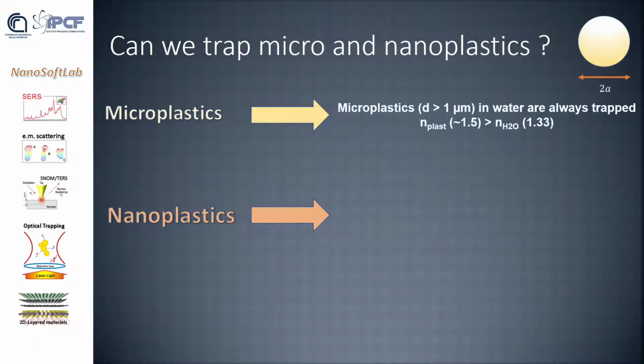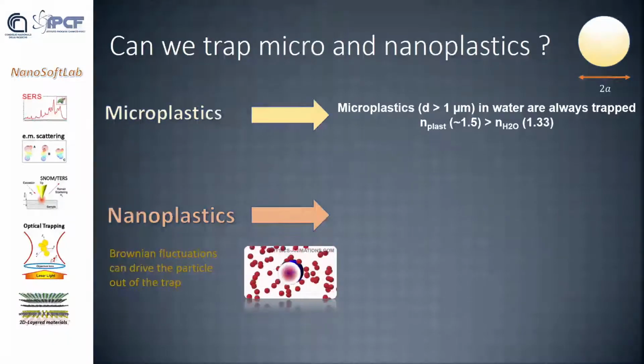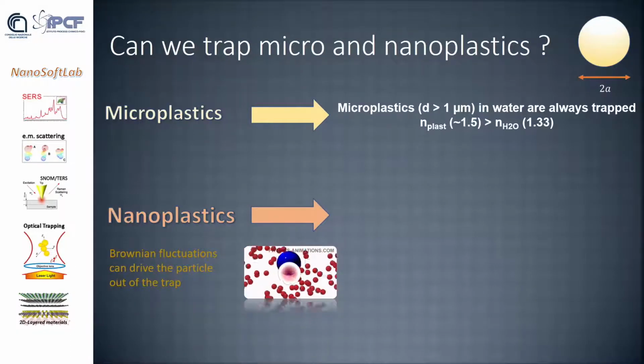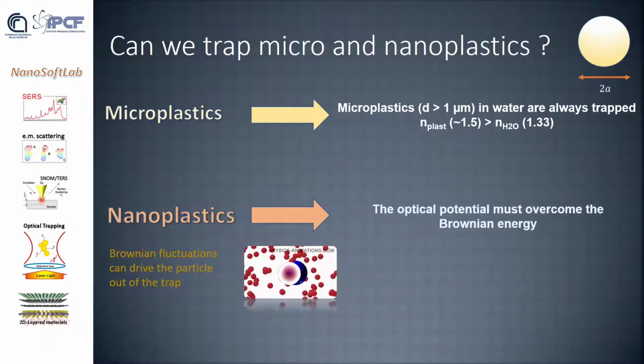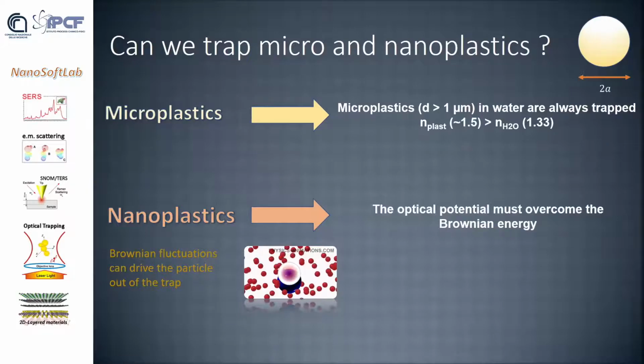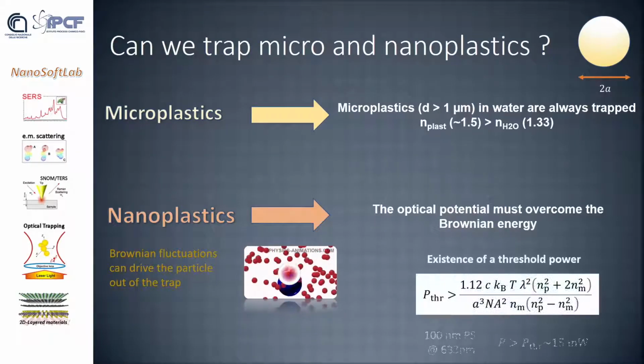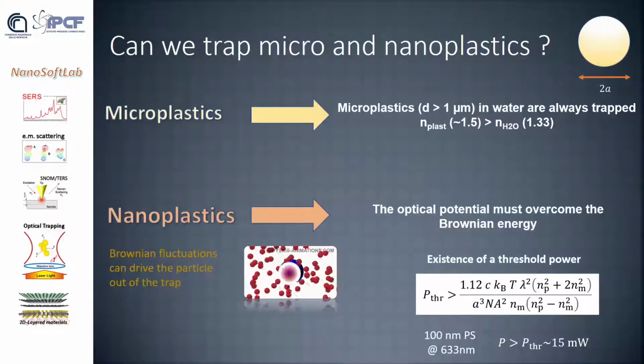So can we trap nanoparticles, micro and nanoplastics? Microplastics can always be trapped since their refractive index is larger than water. For nanoplastics, since there is Brownian motion, it will tend to push the particle away. But if we use a laser source strong enough, for example for 100 nanometer polystyrene at 633 nanometers, we need power higher than 15 milliwatts, we can trap them.